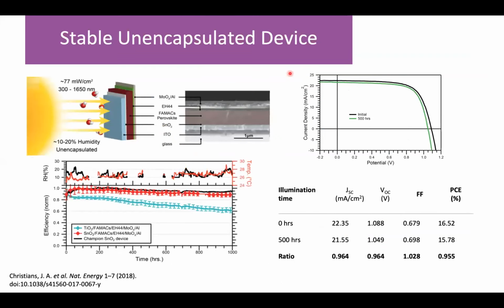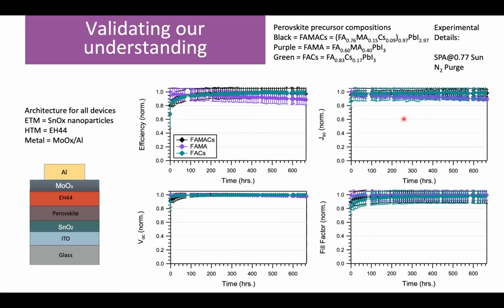And we were subsequently able to show, so this was reported in Nature Energy a few years back, quite nice performance for quite nice efficiency devices at that time. And not only that, we were able to show that while the active layer was important, and again, this is why I have this skewed perspective, since the interfaces are kind of my gig, we're able to make devices that have really quite nice stability across the different active layer compositions, which means that we can tune the electronic gaps around and still maintain quite nice stability.